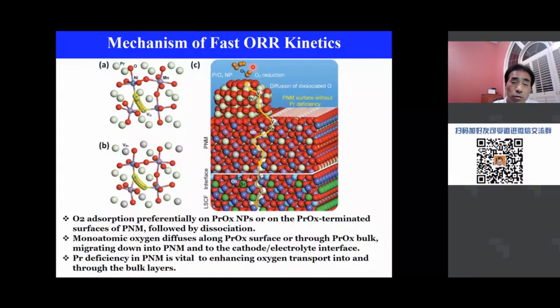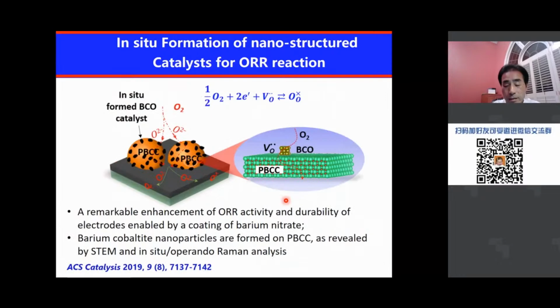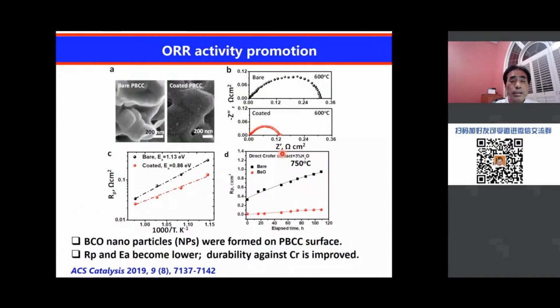And once the oxygen is incorporated into praseodymium oxide, then it goes through the channels of the PNM, then disappears in the LSCF electrode. Another example is that here we create nanoparticles, barium cobaltite nanoparticles, on PBCC. Once again, the geometry or the configuration is similar. Basically, the nanoparticles have high catalytic activity, and that enhances the properties.